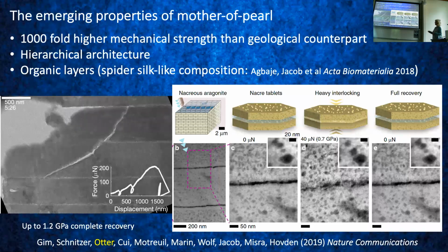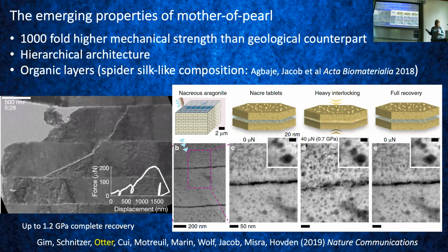And the reason why this works, which of course would not work with normal geological aragonite, is because you have these many little organic inclusions here which change their shape when you press. You can see here you have 3 blobs, there we only have 2 blobs, but when you release you go back to 3 blobs. That's one reason. The other reason is you have these soft materials, this interlamellar organic sheet between the tablets of aragonite, and while the aragonite behaves like a monolith, these sheets in between stop the crack propagation. Whatever happens, it's the combination of this organic and inorganic material that makes it so high performing.